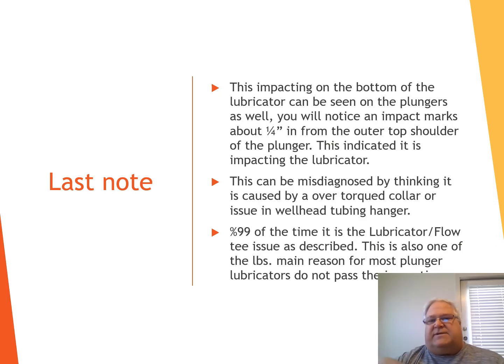This impact on the bottom of the lubricators can also be seen on your plungers many times. If you're pulling your plungers and you're inspecting them, if you look at the very top outer edge of the plunger, many times you'll see an impact mark all the way around that outer edge of the plunger, about a quarter inch in.